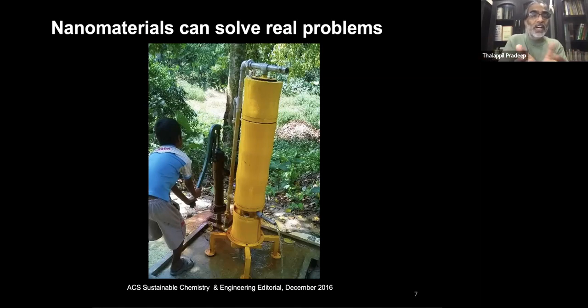About 7 kilograms of these nanomaterials are charged in this filter, along with many other materials. That is why this is a little bit higher in height. The water that comes out is clean, as I said. You can get about 1,000 liters of water per day. And this unit runs at that concentration for about 2.5 years without changing any medium in this. There is no electricity. Directly this water comes out.